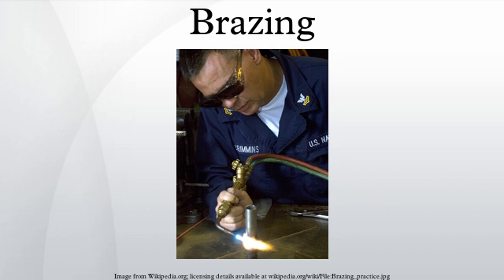Vacuum brazing. Vacuum brazing is a material joining technique that offers significant advantages: extremely clean, superior, flux-free braze joints of high integrity and strength. The process can be expensive because it must be performed inside a vacuum chamber vessel. Temperature uniformity is maintained on the workpiece when heating in a vacuum, greatly reducing residual stresses due to slow heating and cooling cycles. This, in turn,